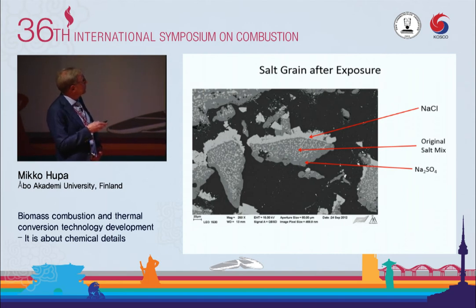So we have the sodium sulfate gray matrix and sodium chloride crystals in that matrix. They were prepared by melting and cooling. So that's how it looks. But with 24 hours in this temperature gradient, the sodium chloride started vaporizing and condensing to different particles, some kind of a vapor transport, which took place quite quickly.